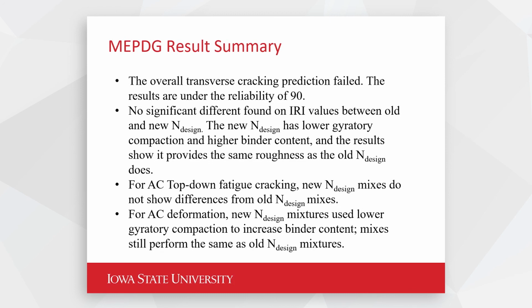So overall, in the project, we demonstrated that the mixes were performing equal or better, and generally had a tendency to be performing better under the new compaction criteria than the old. The one caveat is in terms of the transverse cracking, which would be related to low temperature cracking, that was an area that needed improvement. We believe, although not confirmed, that the field mixes would be meeting or exceeding that criteria now with the newer binder specification put into place.